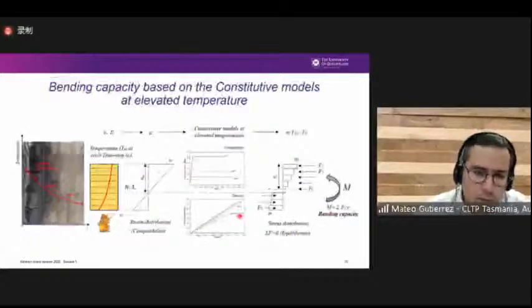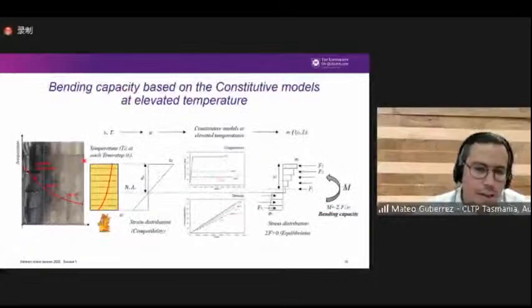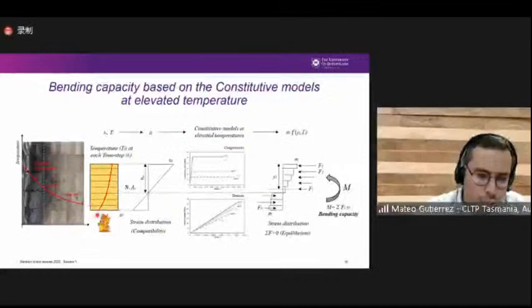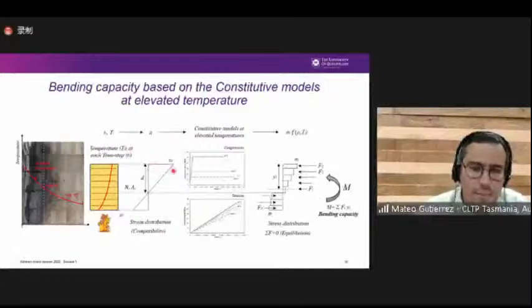So basically the model at elevated temperature is that we have our cross section, we have a temperature profile, and at each time step, we will have a different temperature in each slice, right? We apply again the same beam theory, but using the constitutive models that we created, we will be able to obtain the mechanical properties at each slice, at each time step, and then we can obtain the equilibrium, do the summation of forces, and obtain the bending moment capacity at each time step. And this is basically what we did.